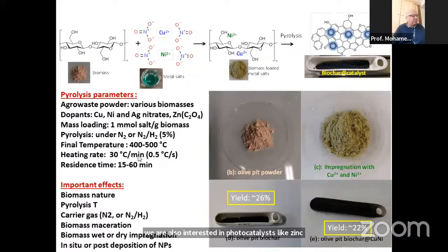Pyrolysis parameters are very simple. For the mass loading, the generic concentration is 1 millimole of salt per 1 gram of biomass. We work under nitrogen. Sometimes we use hydrogen to boost the reduction of the metal ions. Usually we work at 400 to 500 degrees, but sometimes from 300 to 900 degrees to check the temperature effect. Usually we use a ramp between 10 and 30 degrees per minute for the increase of the temperature in the tubular furnace.